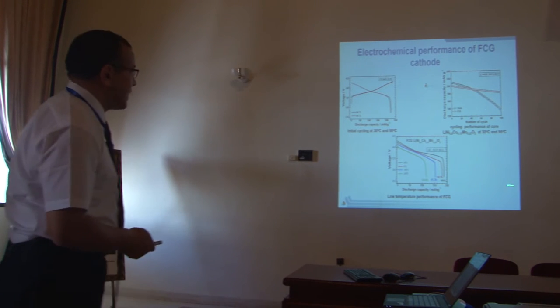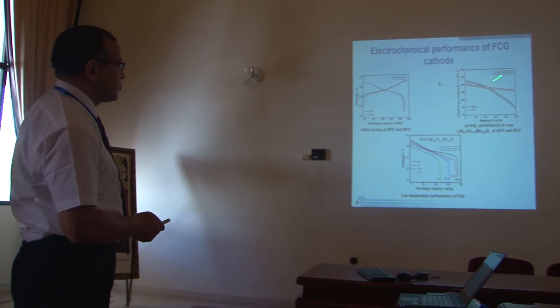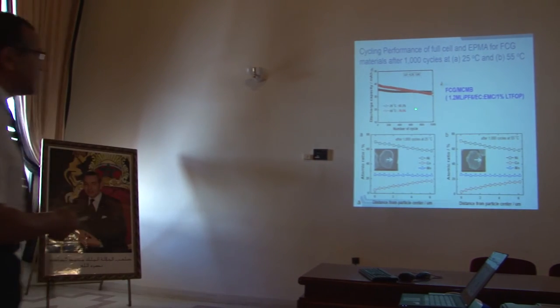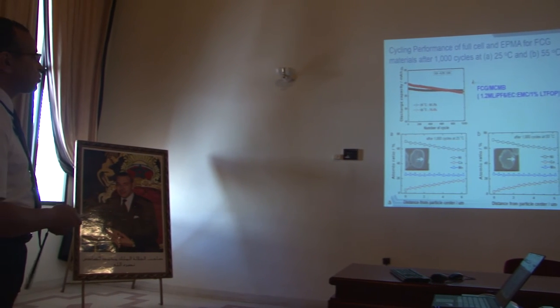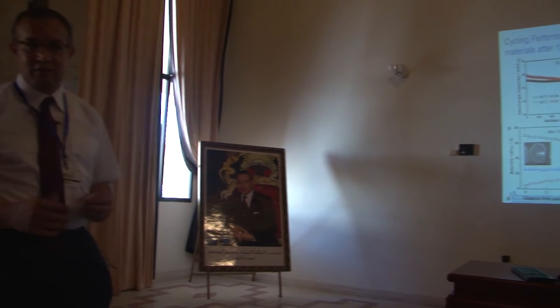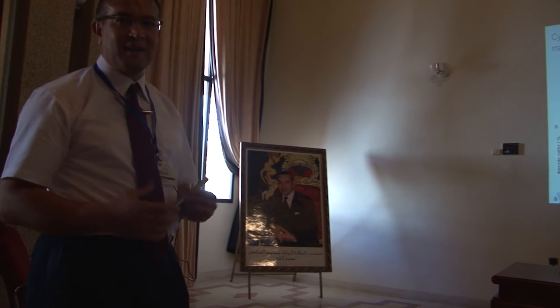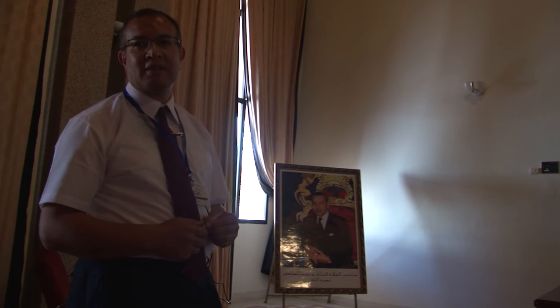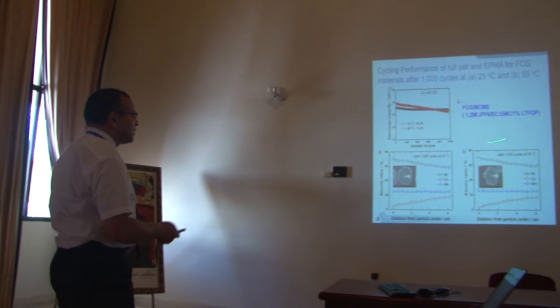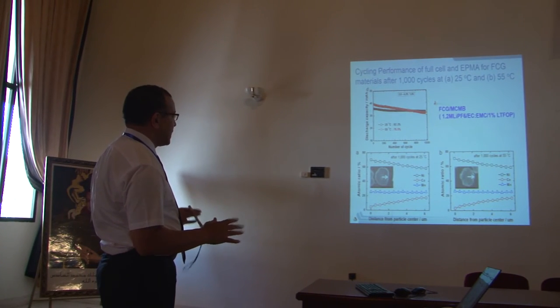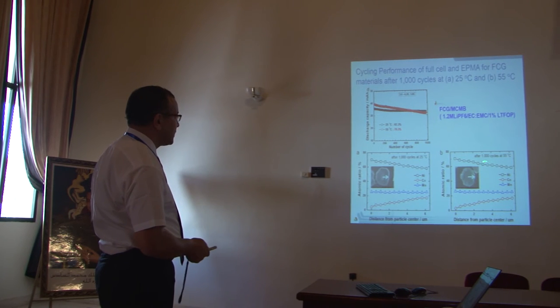And here are some examples where we operate at 4.3 volt. But I will show you this, it's much more interesting. This is a full cell. We have an additive to protect the carbon, since we are operating at high temperature. So you can get 1,000 cycles with the high nickel ratio, which is very, very impressive, because with NCA, at these high voltages, 4.5 volt or 4.3 volt in this case, it's impossible to get 100 cycles. It's just impossible. And the gradient structure does not change after 1,000 cycles, both at room temperature and high temperature.